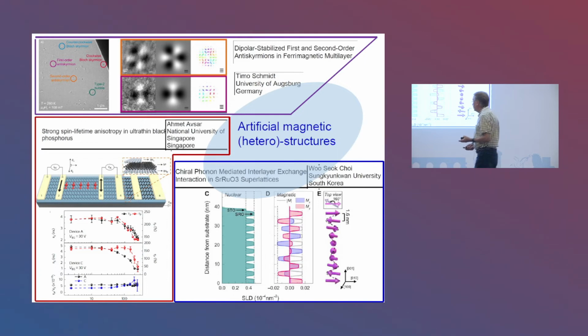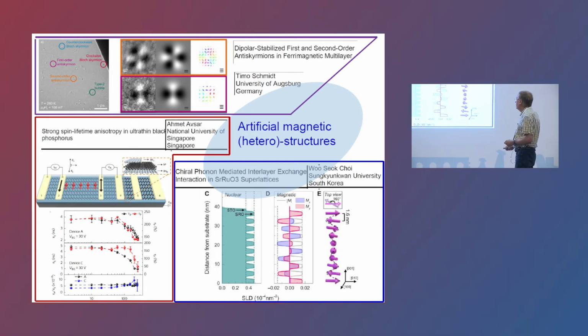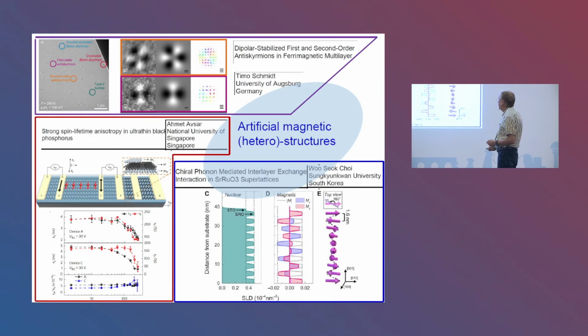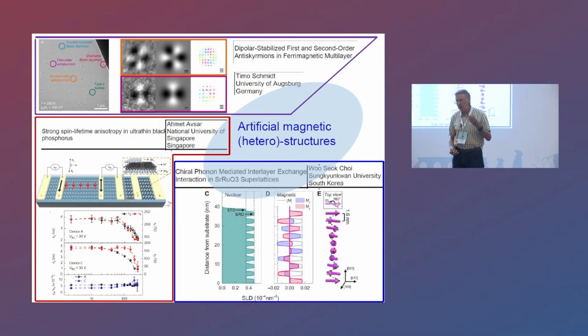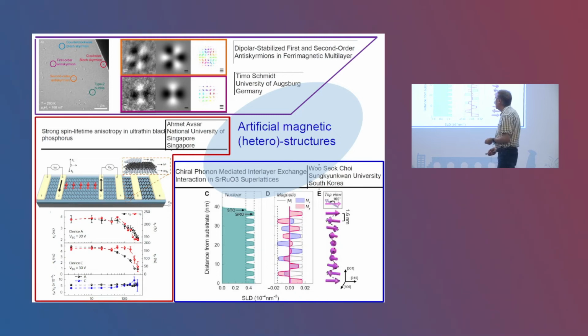So there were also materials presented in this conference which themselves are not magnets, but provide interesting spin phenomena. And one of those presentations which I liked very much personally was the report on the spin-lifetime anisotropy in ultra-thin black phosphorus given in a plenary talk by Ahmet Avsar, I think on the first day of this conference, where it was found that, for instance, the spin transport is very anisotropic in this material. So it's very different if it runs along the zigzag edge or along the armchair edge. And more importantly, it was found that the spin relaxation length in this single layer of black phosphorus is extremely long. It amounts to several microns, which is really a very spectacular observation.